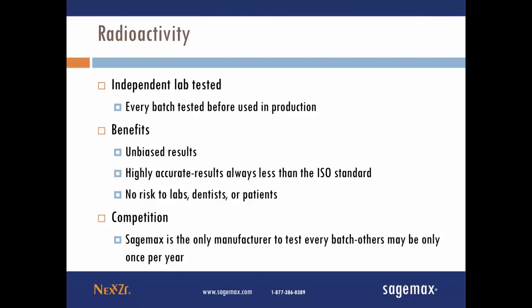So again, for radioactivity, this is something that is very important. The ISO standard is pretty strict, and we hold ourselves to an even stricter guideline. We test our radioactivity on every single batch of material, and we can guarantee to our labs, dentists, and patients that there is no risk of radioactive traces in our zirconia. Unfortunately for our competition, some of them we know do test once a year, but we know that not all of them actually test at all.